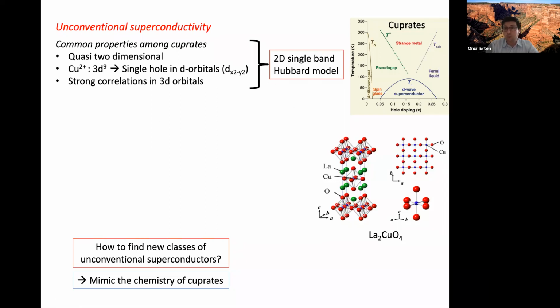And even though this is, of course, a toy model, and it's still questionable if one can reproduce all the different phases in cuprates by just using the two-dimensional single band Hubbard model, the answer is probably not. But at least it's a good starting point, and probably a good way to get a d-wave superconductor. So the goal is to mimic these three properties such that it gives rise to a two-dimensional single band Hubbard model. That's the goal. All right, so why nickelates? Why nickelates? And the answer is actually almost trivial. Nickel is next to copper on the periodic table. So if you want to form 3d9, what you just have to do is, instead of having 2+, you just need to have a nickel 1+. Okay. That's it.